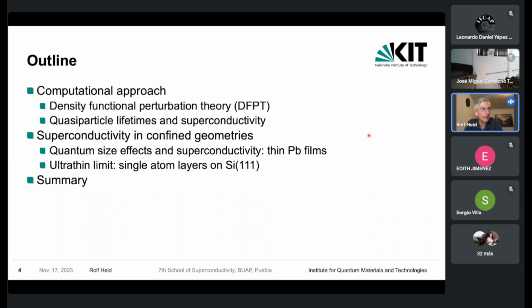In the second part, I apply this to a specific type of problem, namely superconductivity in confined geometries. And there I distinguish two different kinds. The first one is looking at thin metallic films, in particular thin lead films, and we'll discuss a little bit how the confinement of the geometry leads to some quantum size effects, which can also be seen in superconducting properties. And then I go to the ultra-thin limit of such films, namely to single atom layers on an insulating or semiconducting substrate, and I will discuss several cases of that in more detail.